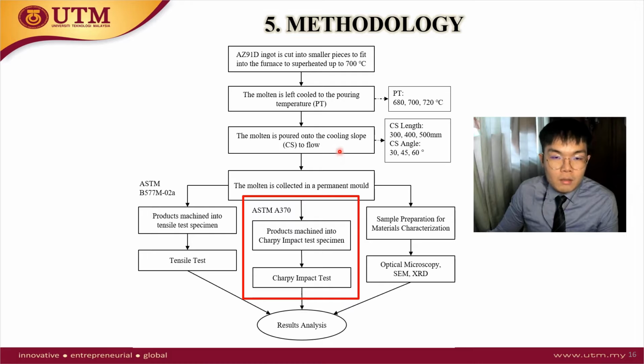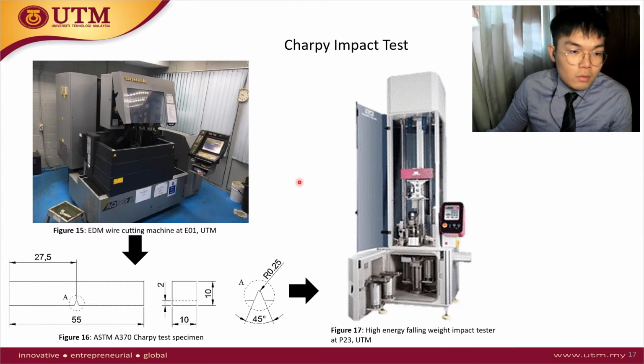The second mechanical test is the Charpy impact test, which measures the impact force absorbed by the specimen before fracture. First we use an EDM wire cutting machine to machine the specimen into the required test specimen geometry, and then we use a high energy falling weight impact tester to perform the Charpy test.